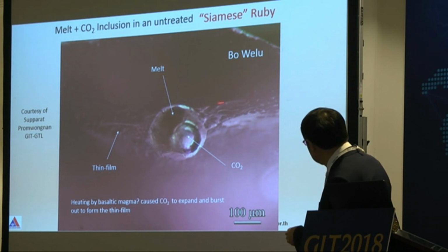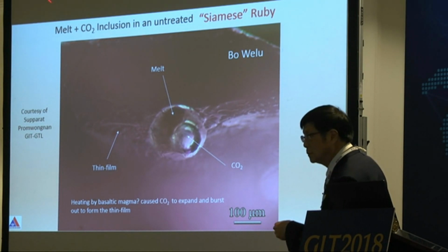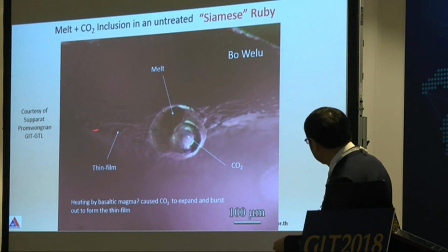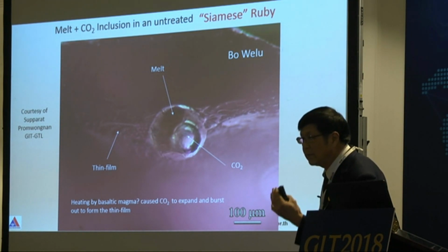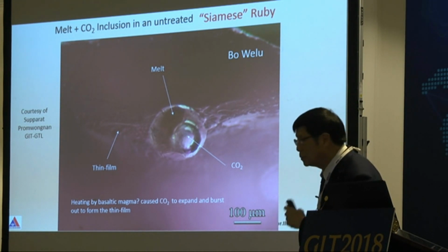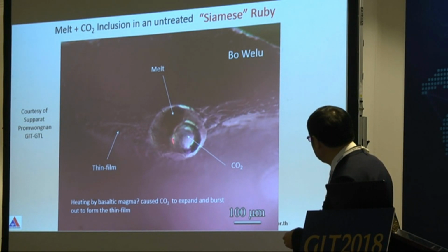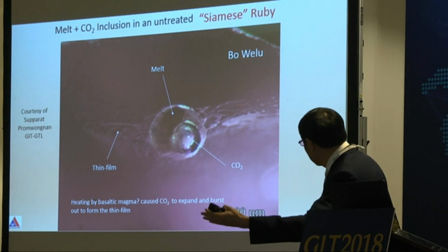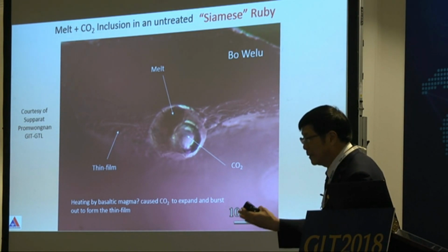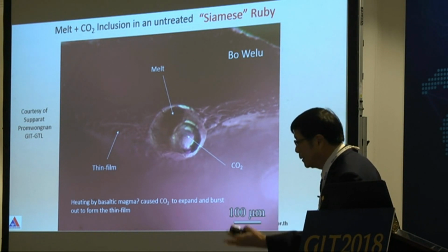And you can see the thin film around it. So what we believe, this is untreated, just picked up from the ground. And we think this kind of thin film was formed by heating from the basaltic magma before it was brought up to the surface. It heated up this stone, and because of the heat, the CO2 expands and then bursts to form a thin film originally from underground. But when you mine it and treat it with heat, then you produce more thin film, a lot of thin film. But originally it does have thin film from the beginning, maybe caused by the heat from the basalt itself.